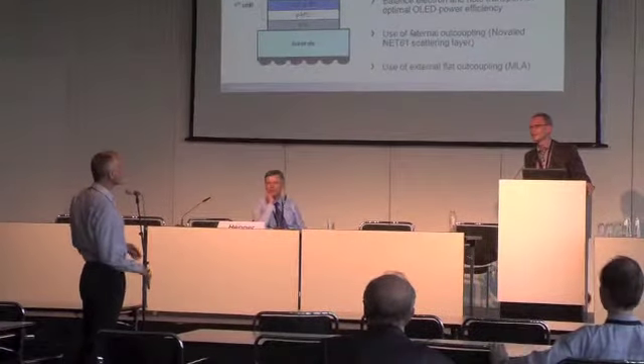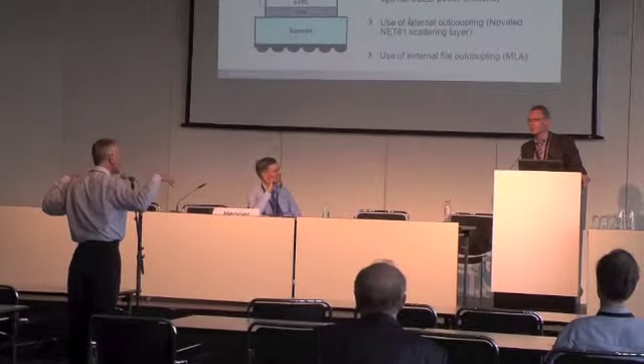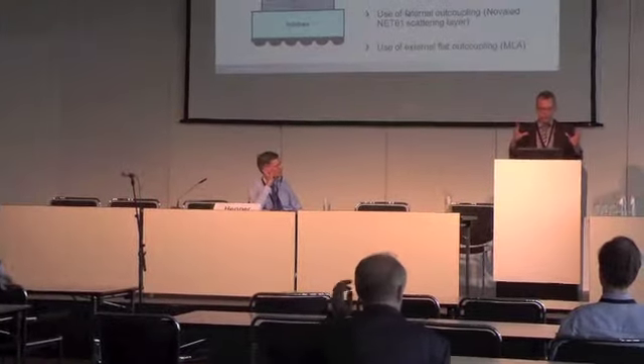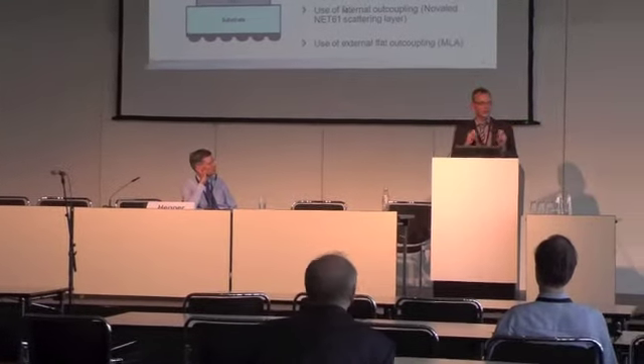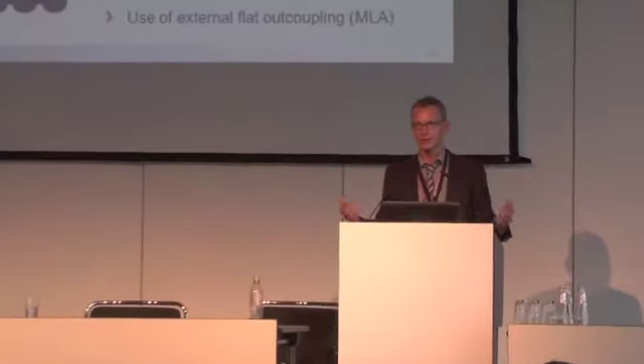Could you comment on which effects limit the lifetime of the displays, especially when we want to have lighting and so on? Lifetime of the devices in terms of efficiency? Exactly. What you do is you create light by the combination of electrons and holes. That means your device has to see lots of current. If you want to create much light, you see lots of current. So this is a degradation factor. If then oxygen and water come in addition, you have light, you have active chemical reagents, and you also have a certain kind of heat that destroys some molecules over time. This is basically the reason why lifetime is limited.